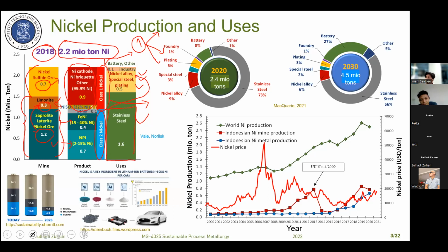Most of the nickel, if you see from this diagram, is used for stainless steel, around 1.6 million ton of nickel. That was in 2018. It is used for stainless steel, and the rest is used for other purposes, for example nickel alloy, special steel, electroplating, battery, etc. If you look at the data from 2020, the nickel produced is around 2.4 million tons. This is the proportion: stainless steel 73%, nickel base alloy around 9%, and batteries around 8%.